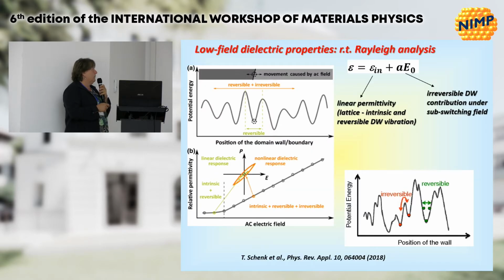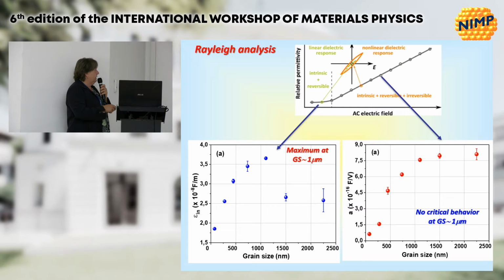Typically, the low field dielectric properties can also be analyzed by Rayleigh analysis, which is quite rich in information because it can separate the field-independent permittivity that is due to the lattice or intrinsic contribution, and reversible domain wall vibrations. The reversible domain wall vibrations are related to the oscillations of domain walls along local minima. Of course, Rayleigh analysis is performed under sub-switching fields, which are 20 times smaller than the coercive field, and we could separate this contribution with a very clear maximum of the field-independent permittivity and with no critical behavior of the nonlinear parameter. So the component that is given by the intrinsic and reversible domain walls shows this maximum, but the others not.